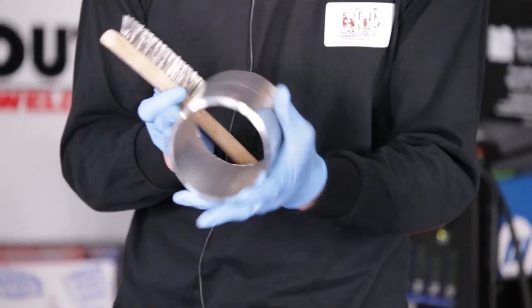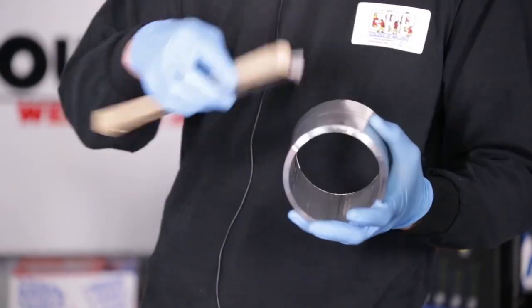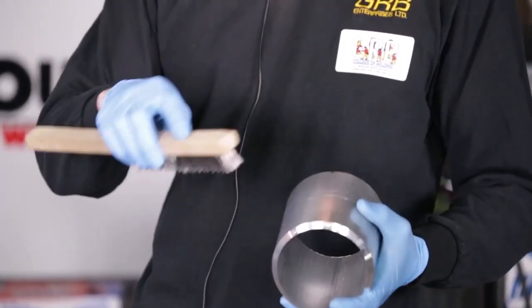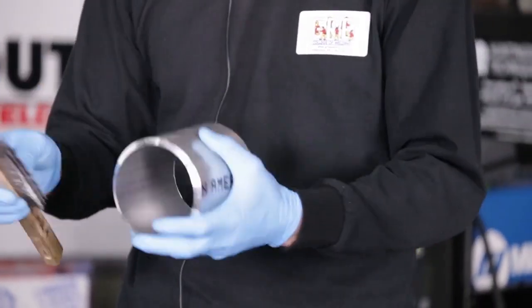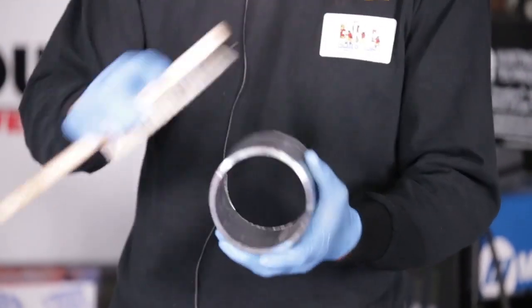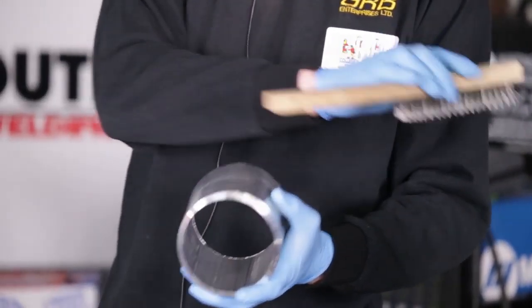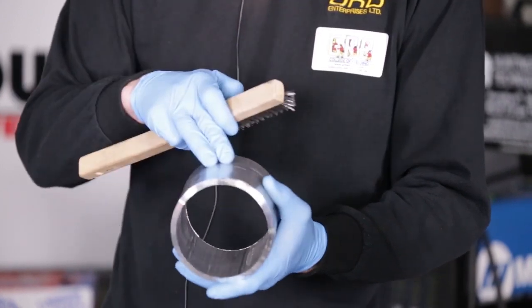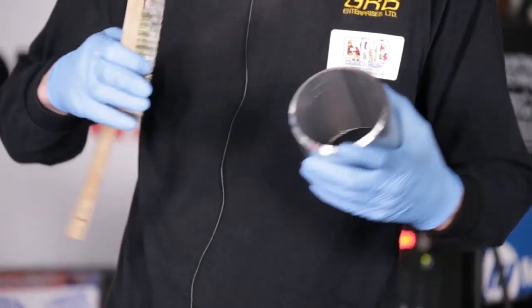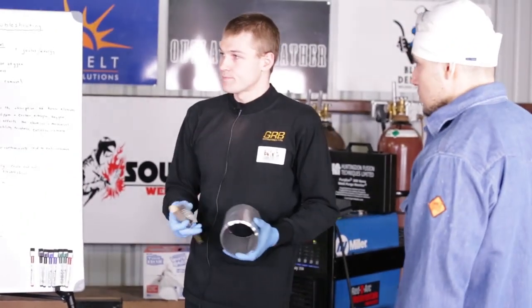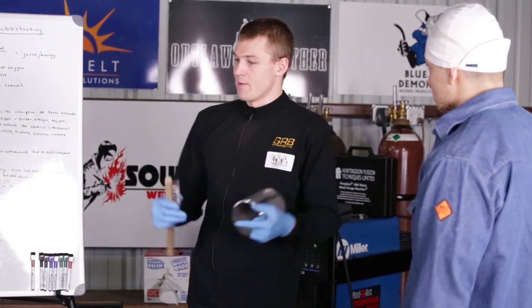He has told me on aluminum, do not, and in other metals too, nickel alloys, stainless, whatever material you're welding, even carbon, chrome, don't go like this, because you brush the oxide off in one direction, and then because this is a very soft material, when you come back, it digs into the soft aluminum and embeds the oxides into the material deeper. So literally it's taking the oxides away, but then bringing it back more. Yeah, and it puts them in deeper.